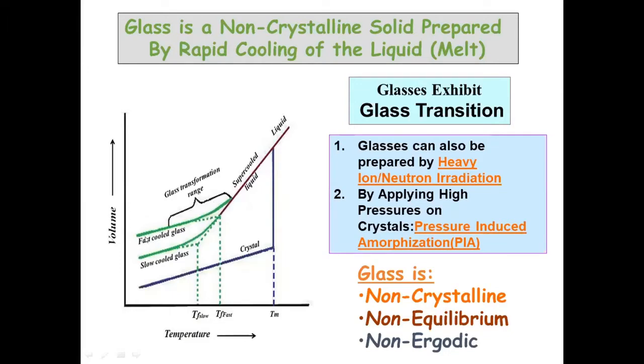And glasses show this glass transition phenomenon in which they enter the supercooled liquid region when they are heated. Now, if you start from the glassy phase and begin heating it, you will first see a supercooled liquid region, and then finally above the liquidus temperature, you will see the liquid. So glasses can be prepared either by rapid cooling of the melt or by heavy ion irradiation or by neutron bombardment. And some materials like ice can also form glasses by applying pressure. This is known as pressure induced amorphization.